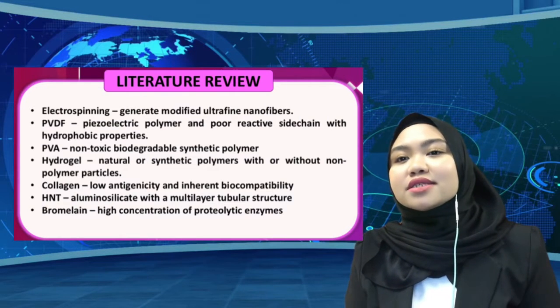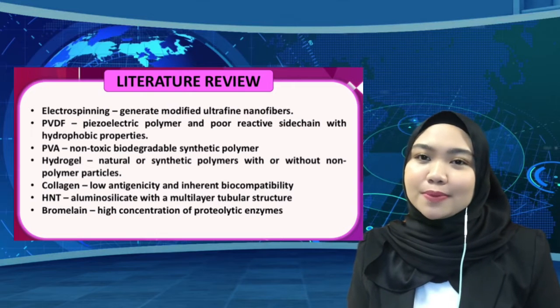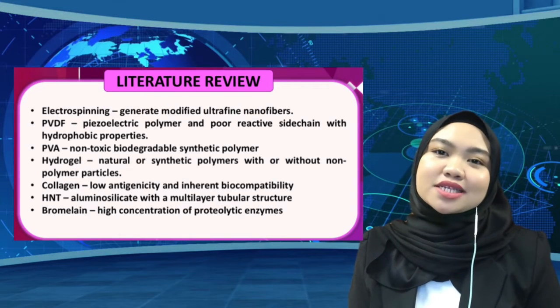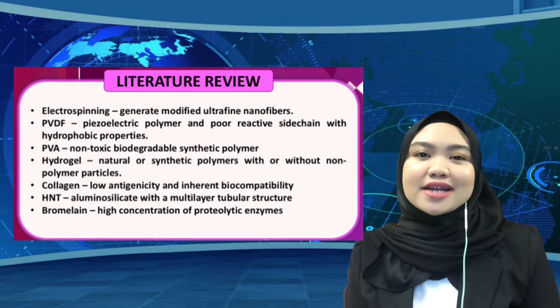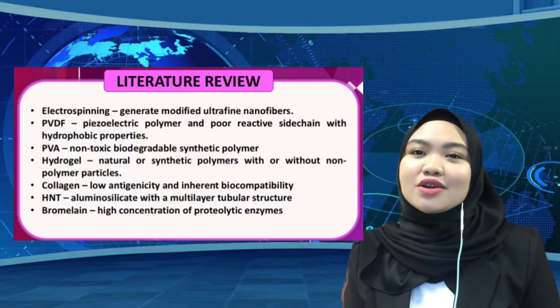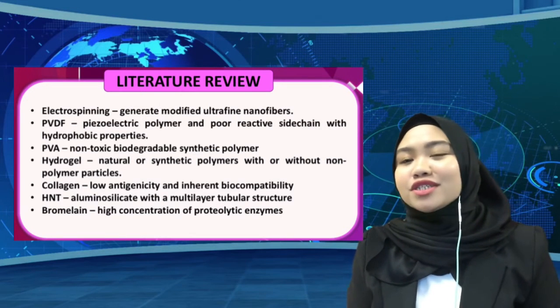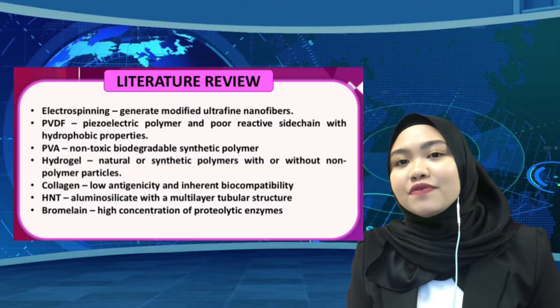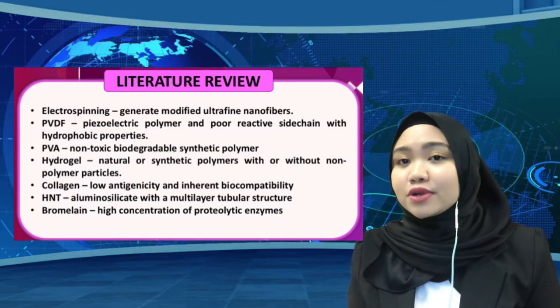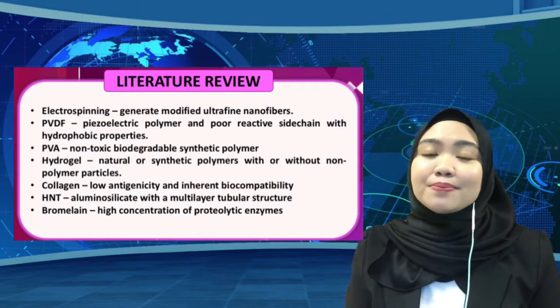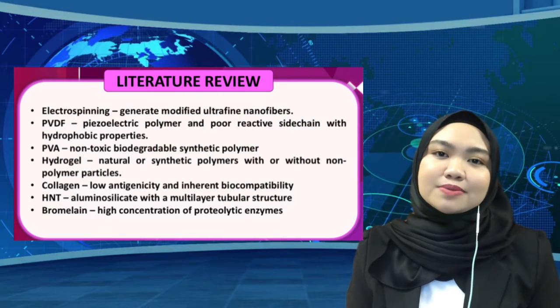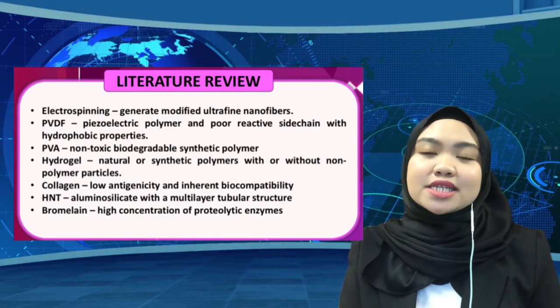PVA is a non-toxic biodegradable synthetic polymer that possesses hydrophilic properties, consisting of a backbone that comprises carbon atoms and pendant hydroxyl groups. PVA was introduced into electrospun PVDF through an electrospinning process to enhance the nanofibrous membrane's biocompatibility by improving the hydrophilicity properties.